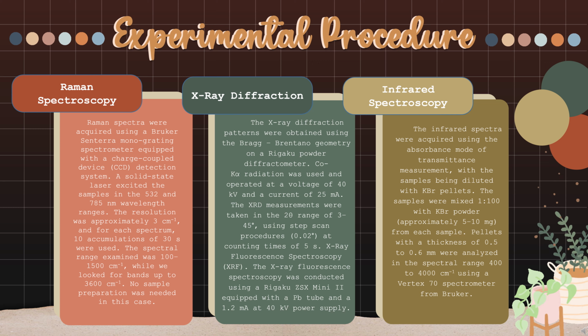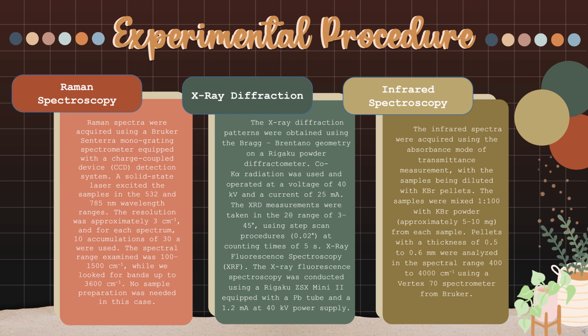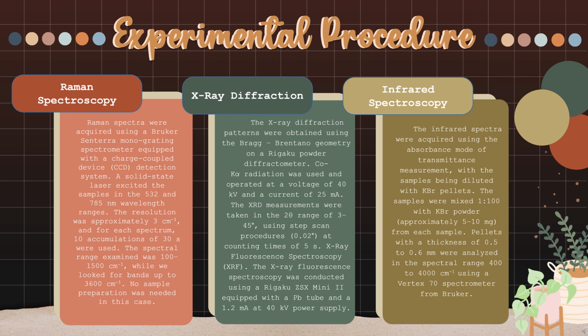Experimental procedure. In Raman spectroscopy, a solid-state laser excited the samples in the 532 and 785 nanometer wavelength ranges. The resolution was approximately 3 centimeters, and the spectral range examined was 100 to 1,500 centimeters, while we looked for bands up to 3,600 centimeters. No sample preparation was needed in this case.